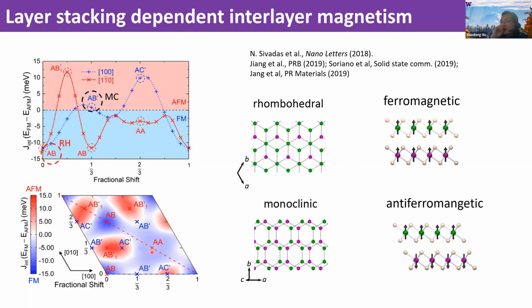There are two interesting structures that are nearly degenerate in energy. One is rhombohedral. This is the structure of the bulk crystal at low temperature, and it appears ferromagnetic. The other crystal structure is monoclinic. This is actually the low-temperature phase structure for exfoliated crystals. That's why all the exfoliated crystals we found are antiferromagnetic. It's different from the bulk crystals, and it's mainly coming from structural effects.